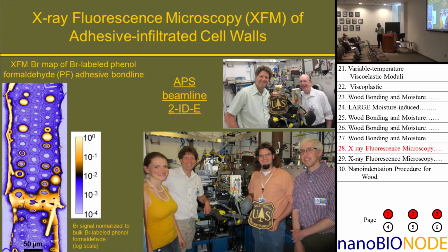For this tool, we took a bromine-labeled phenol formaldehyde. We made wood adhesive bond lines. We cut a 2-micron thick wood section, and then did X-ray fluorescence microscopy, which is done at APS Beamline 2-ID-E. This was the beamline scientist, Sophie-Charlotte Gleber. And this is Chris Hunt, Chuck Frihart, and Daniel Yelle, who are fellow scientists at Forest Products Laboratory, who are really chemists and were able to make this bromine-labeled phenol formaldehyde and also really understand wood adhesion well. With this technique, you have a 200 nanometer beam that you can raster over this 2-micron wood section, and from the fluorescence signal, you can map out and very accurately quantify the amount of bromine that's in the wood cell wall. Because every link on the adhesive polymer had a bromine, that's directly related to the amount of adhesive that's in the wood cell wall.